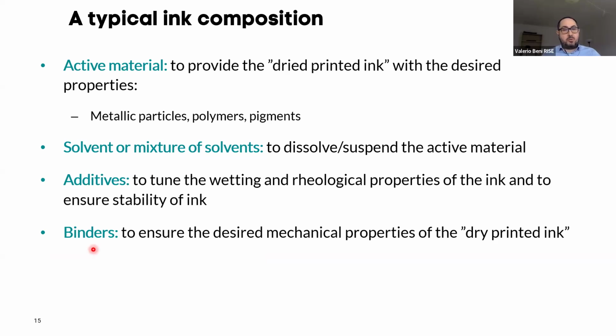A binder ensures that the developed ink stays on the surface after drying. I think you can understand this empirically. If you have a suspension of water and some particles, say sand, when you put it on a surface, they stick nicely together when they are wet, but when you dry it out, they become very dusty and can fall off very easily. So you need a system called a binder that keeps them in place when the ink is dry.